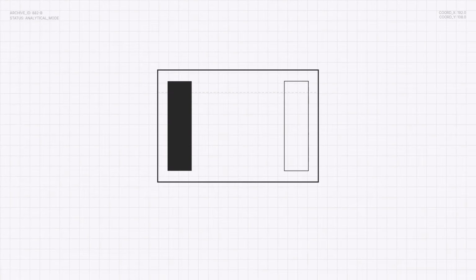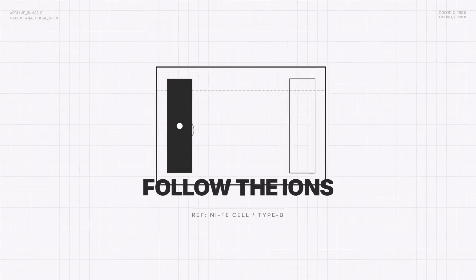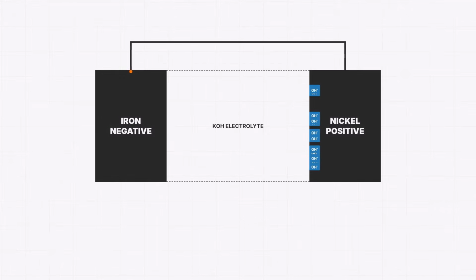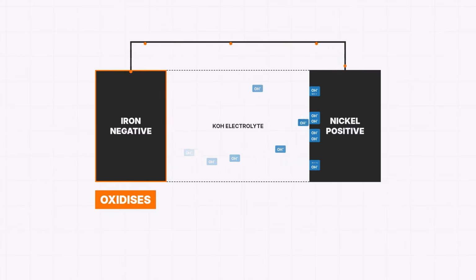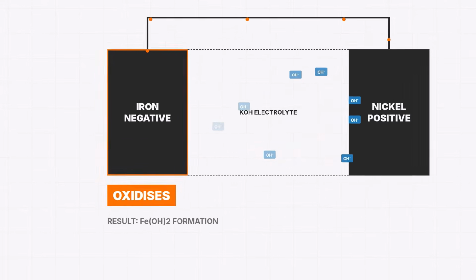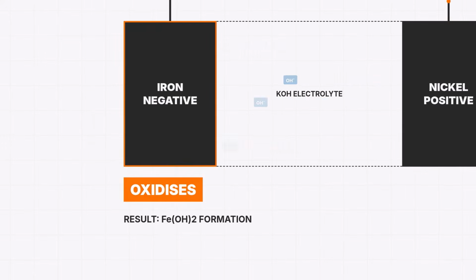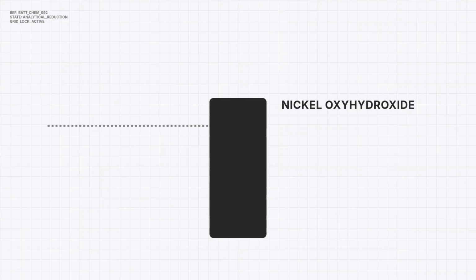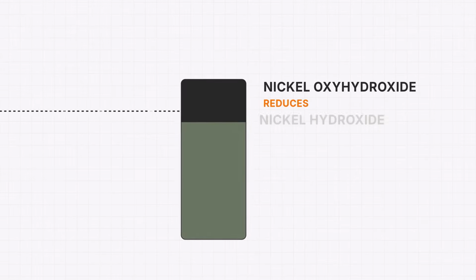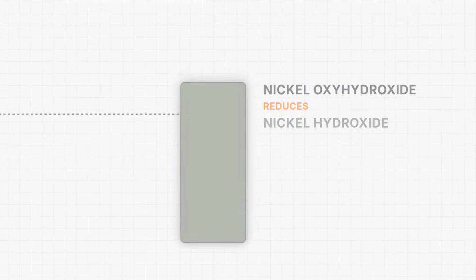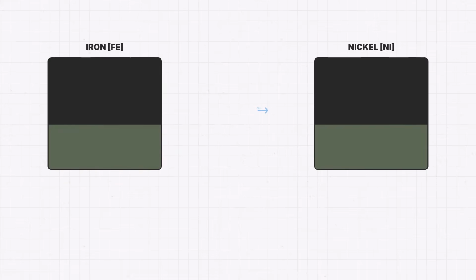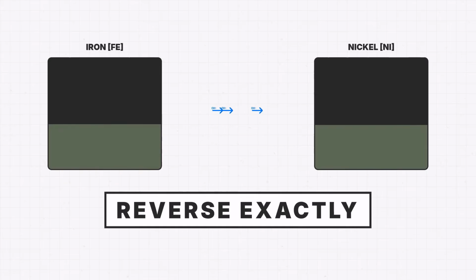To understand how a nickel-iron cell works, you have to follow the ions. During discharge, the iron negative electrode oxidizes. Iron atoms release electrons into the external circuit and combine with hydroxide ions from the potassium hydroxide electrolyte to form iron hydroxide. Simultaneously, the nickel oxyhydroxide positive electrode reduces. Nickel ions accept electrons from the circuit and combine with water to form nickel hydroxide. The electrolyte carries hydroxide ions between the electrodes, completing the internal circuit. During charging, both reactions reverse exactly.